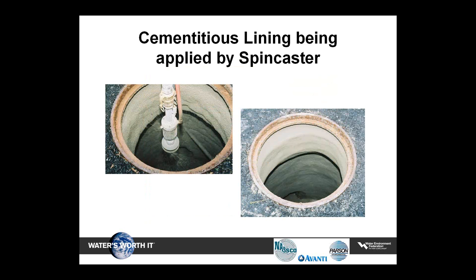Wet shotcrete spraying, either by gun or spin caster, is the most common application method for these products, but most can also be applied by trowel if necessary. Recommended application thickness is a minimum of 1/2 inch, which can be increased depending upon the product's capabilities, along with engineering design parameters that may be part of the project specifications. The products are finished using a steel trowel to compact the material and close up the pore structure. A subsequent brush finish is optional and may be performed if desired.